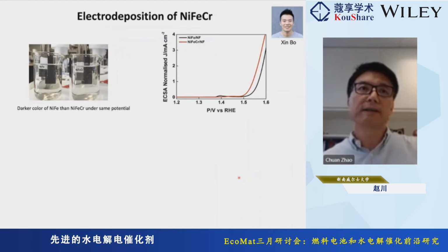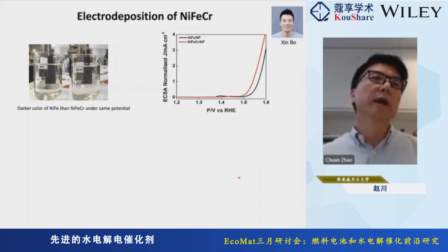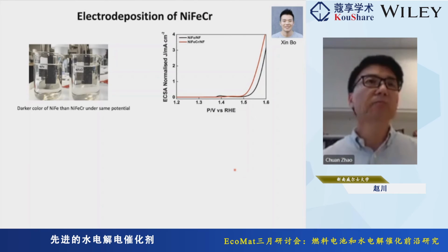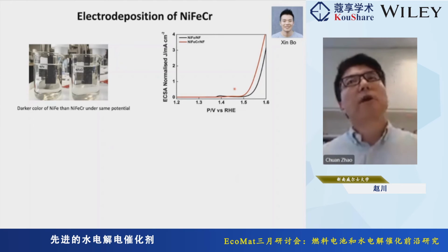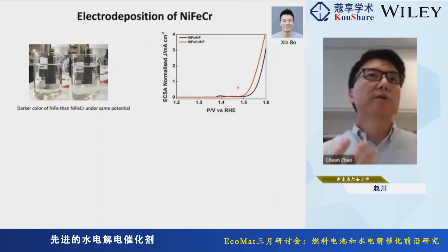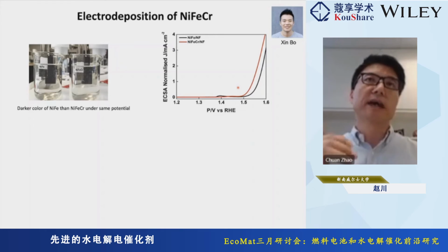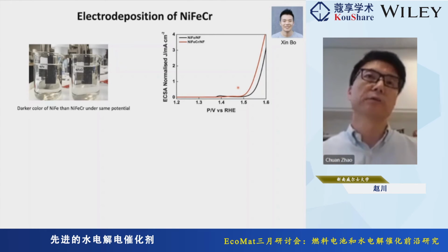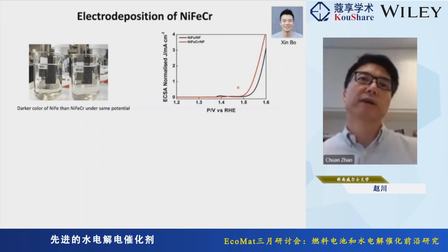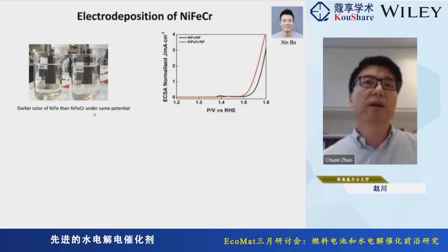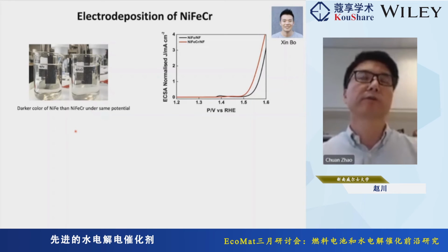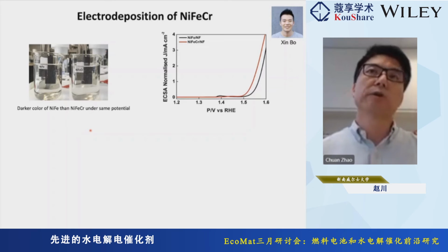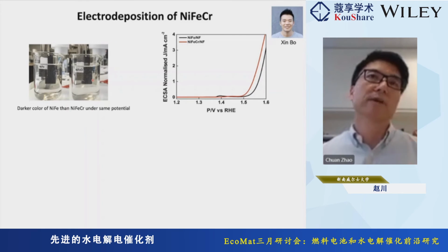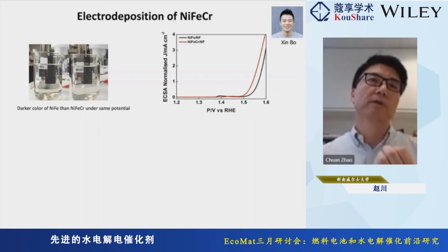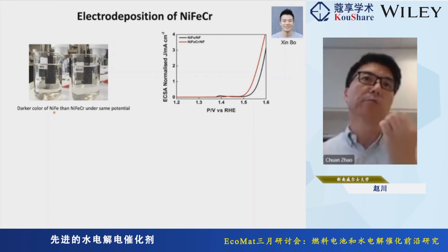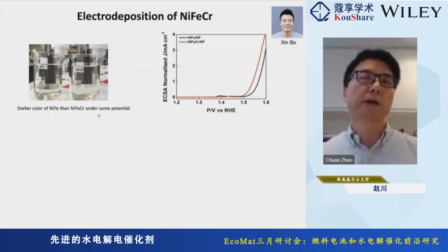I will use nickel iron chromium as an example to explain some other progress in this area. Xin used the simple electrodeposition method. He just added chromium into the electrodeposition bath, and then he got a nickel iron chromium coating on his nickel foam substrate. We then used that electrode for doing OER. What we immediately noticed was that the nickel iron chromium electrode appeared as a lighter color compared to the nickel iron under the same applied potential.